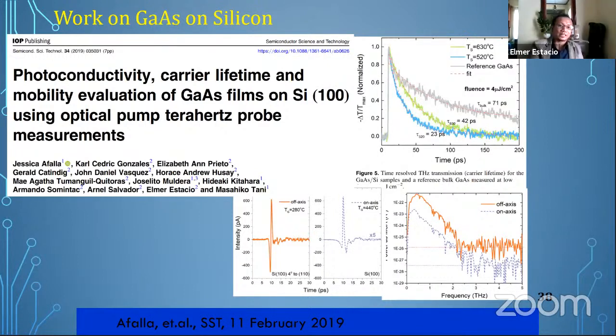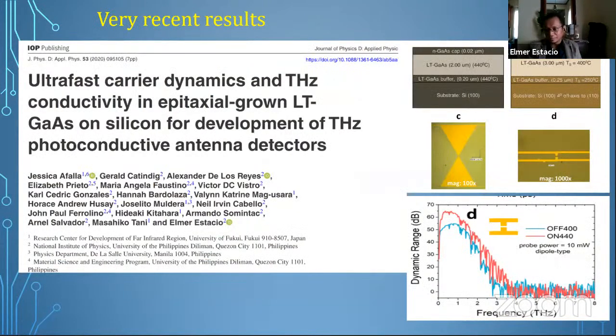First, being able to successfully grow gallium arsenide films on silicon, we were able to show how we are able to generate terahertz radiation using these layers. This was just last year. Of course, we've been working on this for a few years back. And with our procurement of some more modern equipment in device fabrication, we were able to finally develop our own photoconductive antenna devices. And this was a follow-up paper to the gallium arsenide grown on silicon.